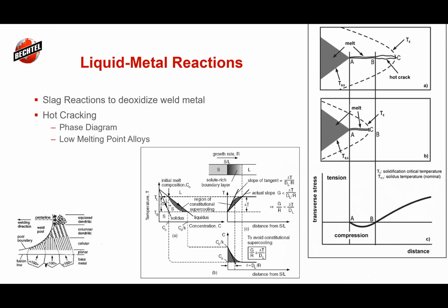The liquid metal reactions as well, as we start heating up and cooling down, we always talk about our joint design and making sure that, as that joint design narrows, we end up with a larger depth to width. And just like that shrinkage, and we know now that it's the allotropic phase transformations, if we have a really narrow depth to width, and that's the same with stainless steel, yes, you can end up with solidification cracking, particularly with the stainless steels, where it pulls itself apart, and that's why we like to have a wider angle. But also those liquid metal reactions can have a tendency, as it starts to shrink on the higher strength, you can put a lot more residual stresses at the toes of the welds.